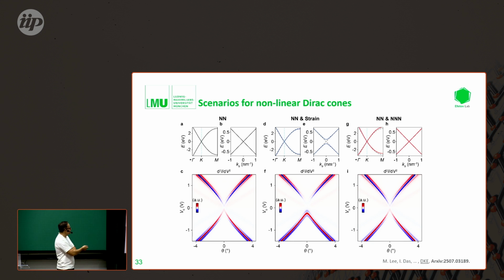The other scenario was of course strain. So we were wondering if strain could produce such a feature as well. But one thing which speaks against strain is that we can test our device in many different regions of the map, and we can change different tips and devices, and all of the energies at which we observed the nonlinearity were the same. And really these strained maps don't produce a nonlinearity, but rather a gap-like spectra due to the misalignment of the Fermi surfaces.